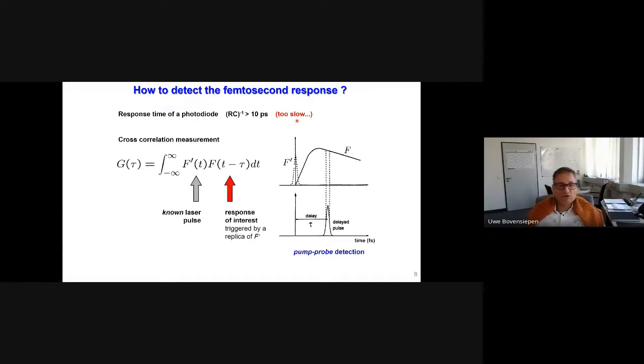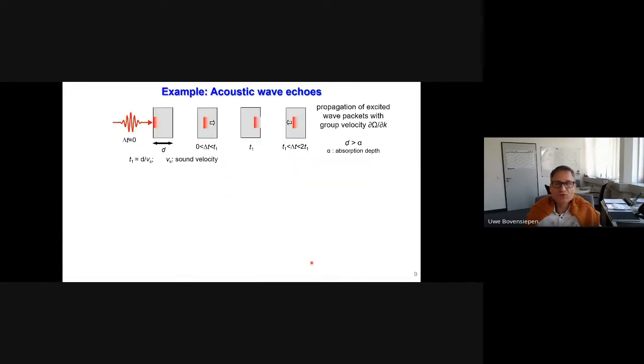What we rather do is a cross-correlation measurement. So we measure this cross-correlation as a function of time delay between two laser pulses. We have a known laser pulse and we have a response in the material that is triggered by a replica of that known laser pulse. And you can view this, as indicated here, as gating the response of the material driven by the first laser pulse with a time-delayed pulse. And we measure here the dependence on this time delay in pump-probe detection. What we assume is that we can do this with a laser repetition rate, and the idea is that we suppose that identical events are captured at these subsequent moments. This is non-trivial, and one has to realize these conditions with quite some thought. But I will show you several examples where this works really well.